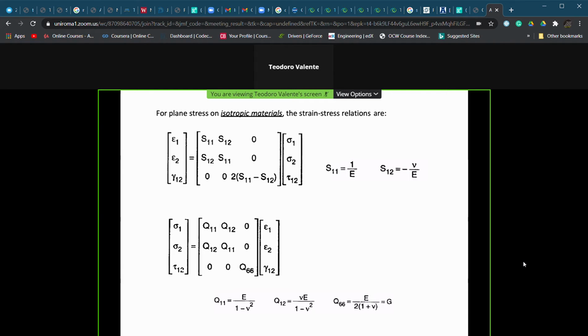If we move to the case of isotropic materials, again with the assumption that we have a plane stress state, we have a further simplification compared with the general case. This is the compliance matrix, this is the reduced stiffness matrix. These are the relationships which allow us to calculate the values of these two matrices. And as you see here, we reduce the number of elastic constants because we have made, in this case, the hypothesis that we have isotropic materials.